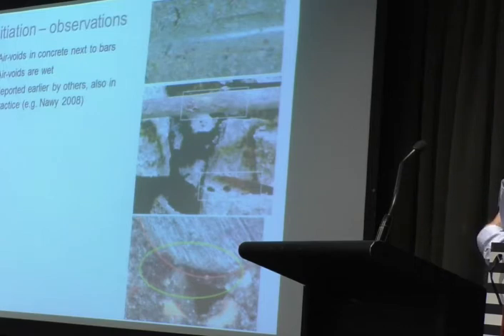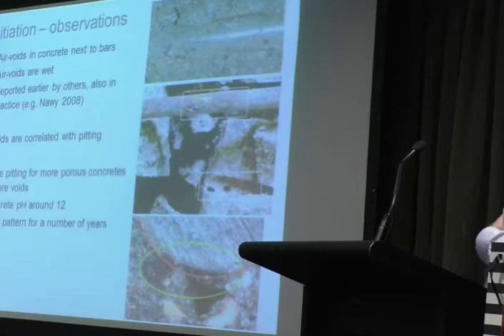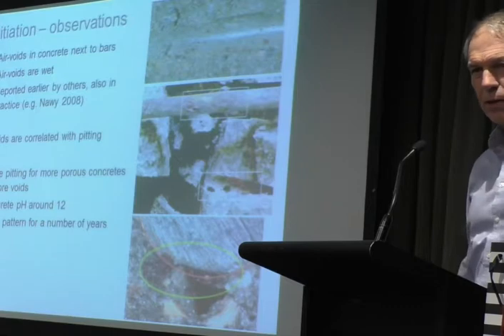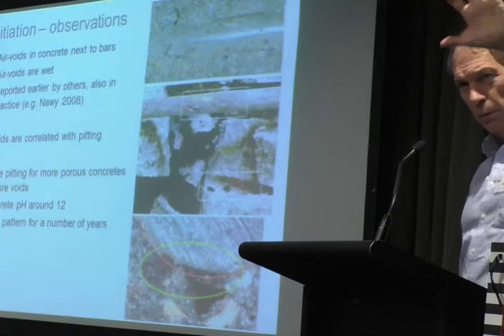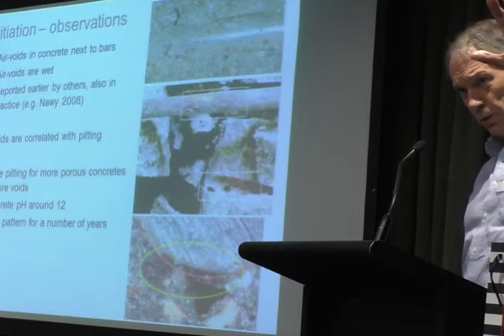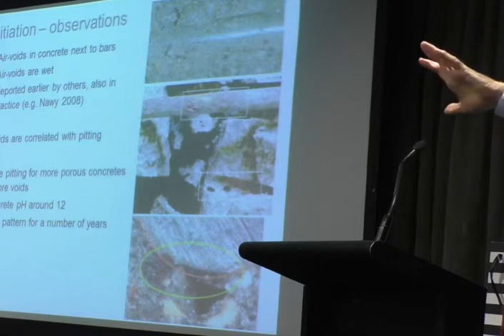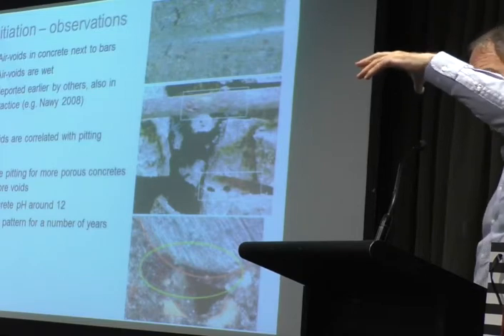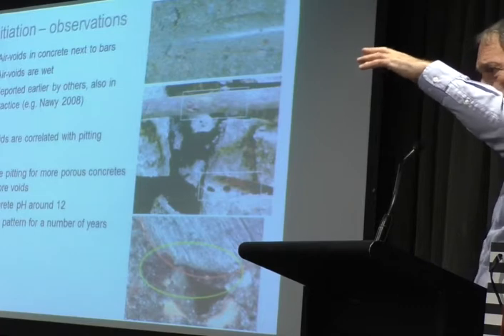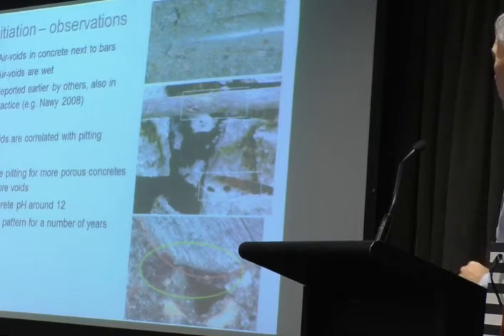And we now know that, of course, this also happens in practice. There are air voids present. The voids are correlated with pitting. And the question is, how do the air voids get there? In our case, because we had all these different ranges of concretes, some were quite permeable or porous, if you like, and others weren't. In the porous concretes, we got bigger gaps between the steel and the concrete, right? So there was more pitting, and that's exactly what we saw.